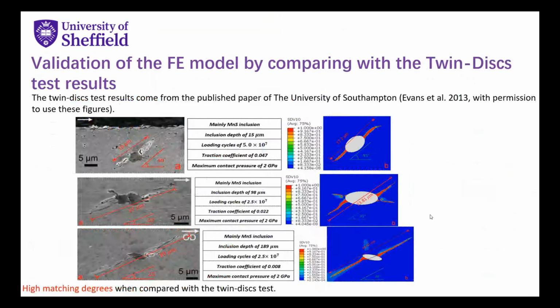To validate the effectiveness of the FE modeling, I compared the modeling results with the twin discs test results from the published paper of the University of Southampton. It can be found that my modeling results are very similar to the real butterfly damage in the twin disc test.